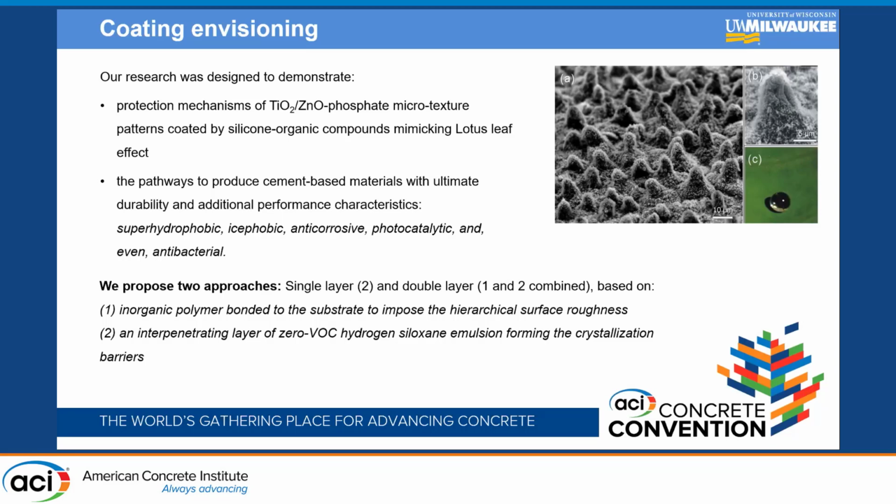This is the surface of the lotus leaf, which is considered a very good predecessor of hydrophobicity and self-cleaning properties from nature. And we can see the surface micro pillars formed from the wax, which are roughly 10 microns in dimension, which are coated with additional nanocrystals. And because of this, the corresponding contact angles are high and the water droplet is very hydrophobic.